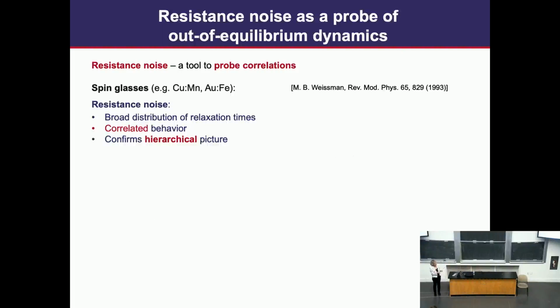In fact, this was demonstrated a long time ago in Mike Weissman's beautiful experiments on spin glasses, where he demonstrated the behavior by looking at higher order statistics. You can actually differentiate between different theoretical models that were proposed at that time, and his data confirmed this hierarchical picture that was proposed by Parisi.